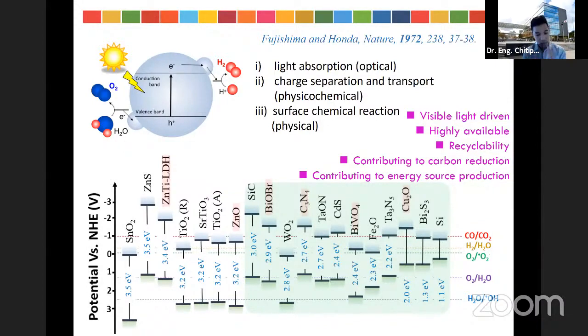So based on the reduction potential of the application, we can decide the energy band gap. Yeah, actually, from the equation, the energy band gap can tell us about the region of light that we can use. For example, if we use visible light, the energy band gap of the photocatalyst should be smaller than 3.0 electron volts due to the light energies. But if we use the UV light region, we can use a bigger energy band gap. For example, TiO2 is around 3.2 electron volts, or zinc oxide is also around 3.2. Yes, but for the application, we need to think about the level of the valence band and the conduction band of the photocatalytic semiconductor.